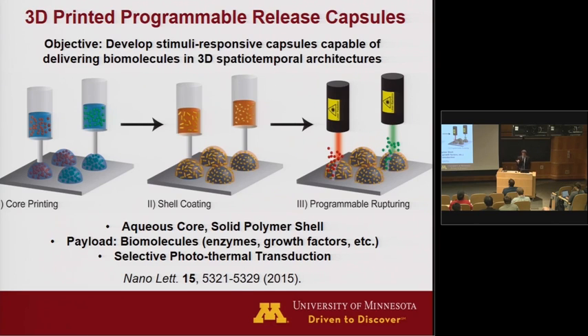And then my student came up with this really clever idea of within the shell of these particles, he puts these gold nanorods which vary by shape. And so the shape variation gives you a photothermal resonance called the plasmon effect here, where they can be triggered by specific wavelengths of laser light to then rupture the shell and then release the contents of the core through that hole that's been generated.